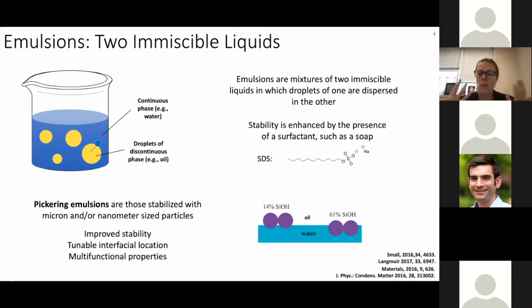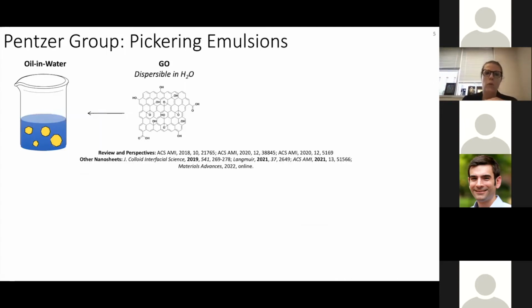And then we can also think about the particles that we use having functional properties. Can they actually do catalysis, for example? Our group really started looking at graphene oxide, or GO, nanosheets. These are dispersible in water. You can add in oils such as toluene and agitate by shear mixing, and you end up with droplets of toluene in a continuous phase of water with the GO nanosheets covering the oil droplet. And these are stable for weeks.